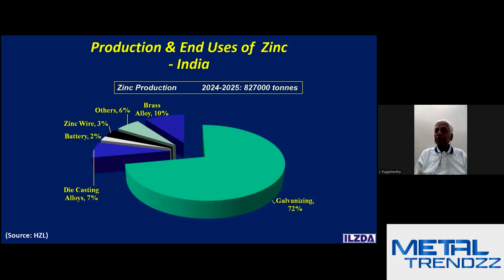And here you should see galvanizing. If you look at the process itself, it's such an excellent process. You clean the steel, dip it in molten zinc, and it forms a metallurgically bonded coating. And this coating is such a product. It has excellent wear resistance, abrasion resistance, rough and tough handling, etc. And the coating never gets removed. And the other beauty is the galvanized coating lasts long for decades and decades. 50, 60, 70 years life you can get in a normal rural atmosphere.